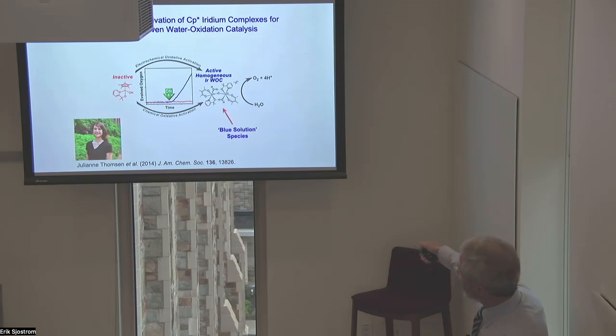degraded, and either using electrochemical oxidation or chemical oxidation, we form this so-called blue solution, which is an iridium dimer. This is a modeled structure of it, which is a phenomenal water oxidation catalyst. I'll show you in a minute. And this is sort of showing here, if we take the precursor complex and turn on a potential of 1.6 volts, which is high enough to oxidize water, we see no water oxidation. This is looking at oxygen that's evolved. But if we make this blue solution, you can see very high rate of oxygen evolution. So it's a very effective water oxidation catalyst.